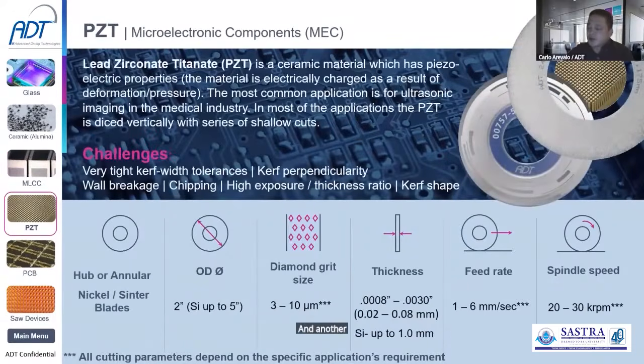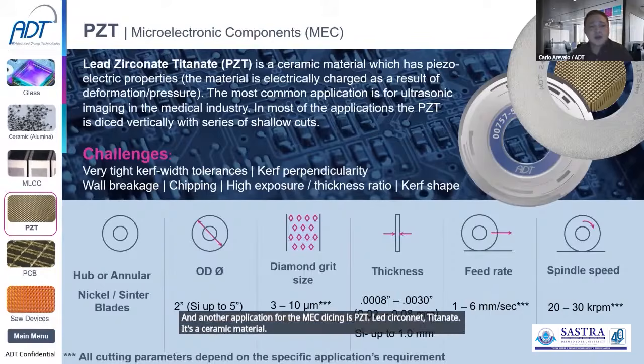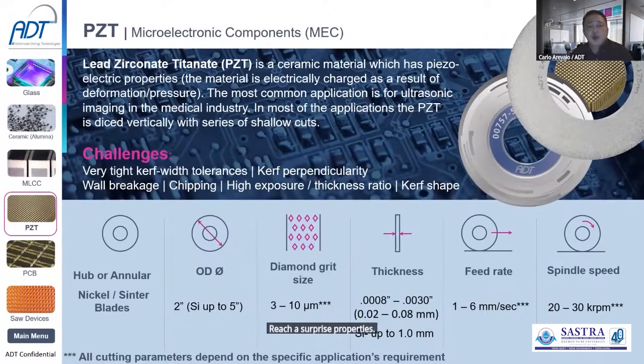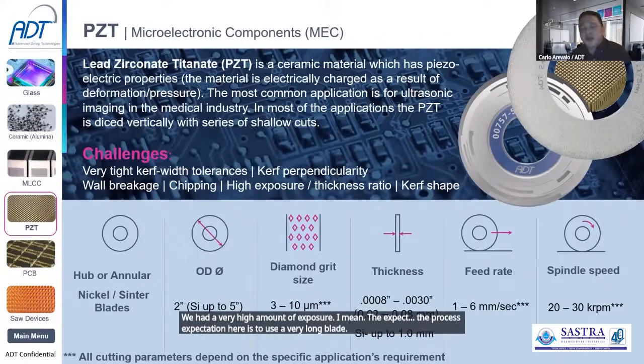Another application for the MEC dicing is PZT, lead zirconate titanate. It's a ceramic material which has piezoelectric properties. The most common application is ultrasonic imaging. So our customers who use this blade are packaging ultrasound transducers, for the medical industry. This blade is expected to be used with a very high amount of exposure. I mean, the process expectation here is to use a very long blade and a very thin cut line.